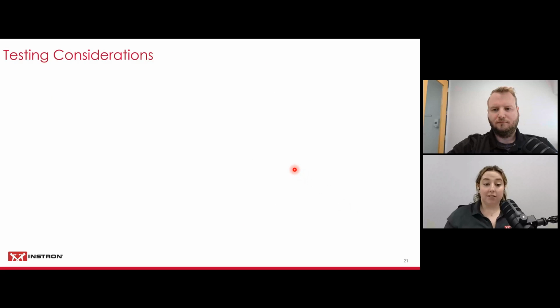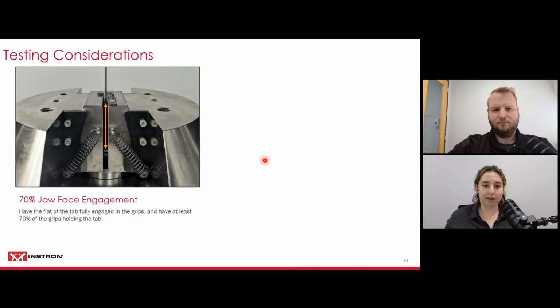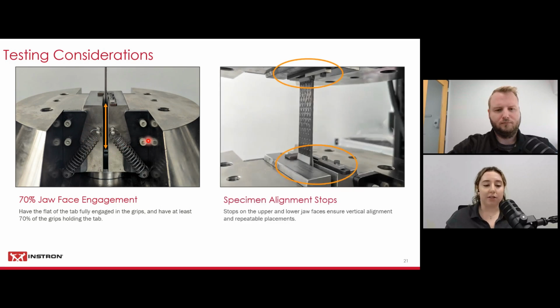Some testing considerations that you want to take into your lab, the following practices: 70% jaw face engagement. You want to have the flat of your tab fully engaged in the grips and have at least 70% of the grips or the jaw faces holding the tab. Not doing this actually risks jaw face pivot at the bottom of the jaw faces, which can risk having your specimen pull out of the grips before even the end of test is done.